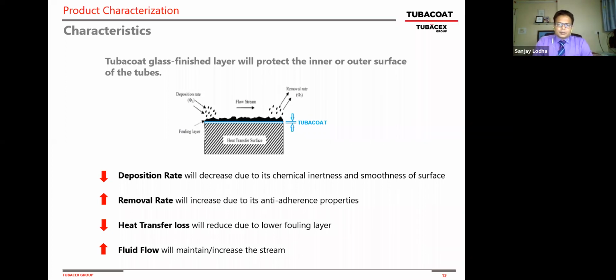When you apply this coating inside the tube, what you see here is that the deposition rate of the particulate matter or the fouling matter will decrease, because the tubes are chemically inert and very smooth, like a glass finish. Also, the removal rate of this fouling material will increase because it will not stick to the surface of the tube. Because of that, the heat transfer loss, which you would have otherwise, will reduce significantly. And since you don't have that fouling and heat transfer loss, your fluid flow, the process throughput, will be maintained at a steady state. That's an important characteristic of the Tubacoat.